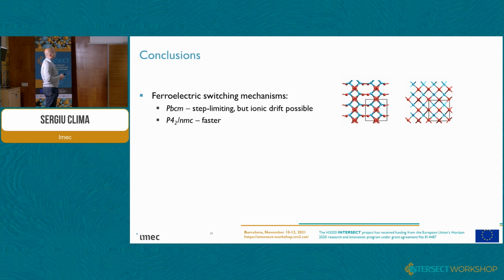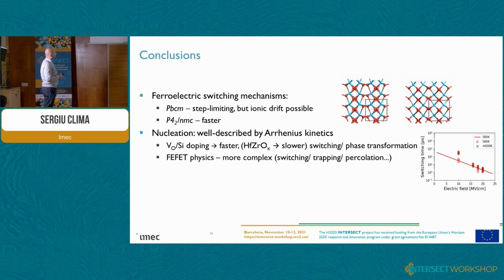So to conclude, there are many mechanisms for ferroelectric switching, but they can be categorized in 2 classes. One is the ionic drift mechanism, which has a higher barrier, so eventually it could be step limiting. However, the tetragonal mechanism, P4-2NMC, should be faster because the barrier height is smaller, and the mechanism itself is rather complicated.